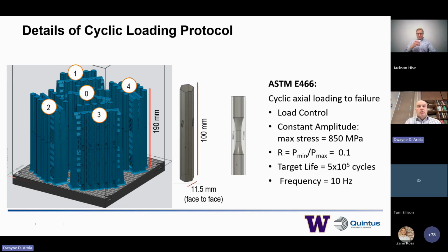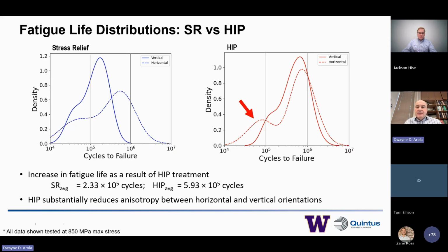We performed that in load control with a constant amplitude fatigue curve with a max stress of 850 megapascal and a stress ratio of 0.1. We were targeting average life of approximately 5 times 10 to the 5th cycles so that we could have manageable fatigue life for all the fatigue samples that were developed by all the partners, and cyclic loading frequency was 10 hertz. All right, so now we're ready to get into the gravy or the good stuff.